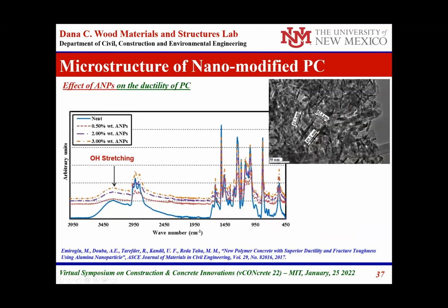It's a very high ductile material. We looked at the microstructure of this nano-modified polymer concrete, and we actually found significant changes happening in the reactivity of the polymer matrix itself that allow this superior ductility, especially with alumina nanoparticles that change the microstructure and the polymerization process in the polymer concrete.